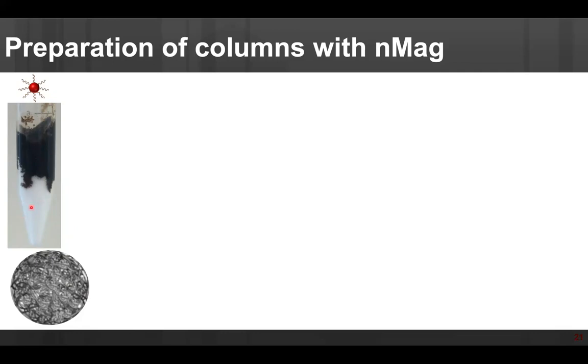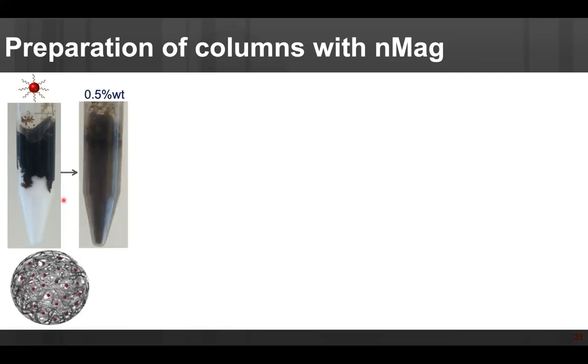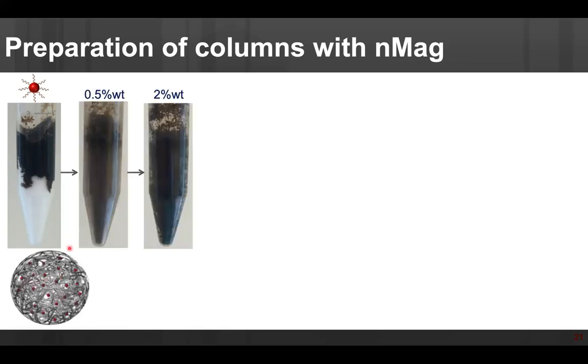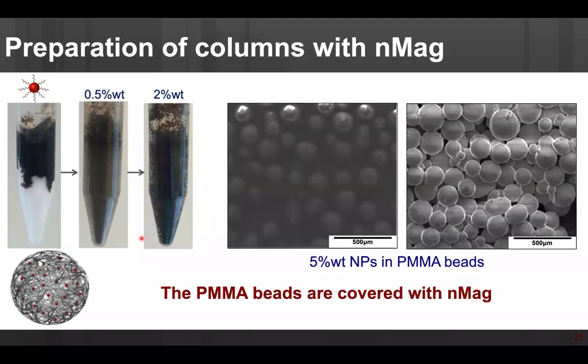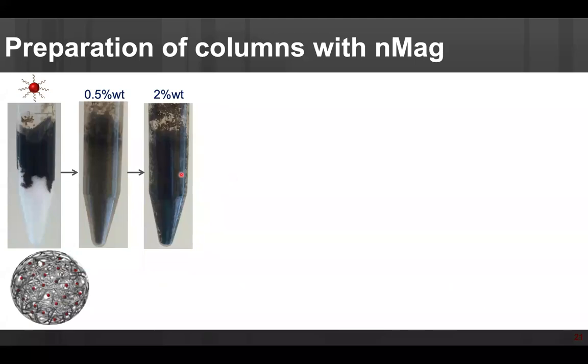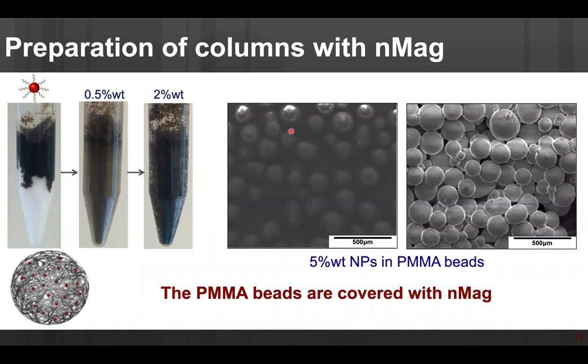So what I thought at that moment is, well, we have these nice polymer beads that we can use as a support. If we stick the nanoparticles on the surface, I start to saturate this one. And as much as I add, I think the highest that I added in here was 2%. And we can see how the bead changes before adding the nanoparticles to after adding them. Now we have a lot of contrast coming from the nanoparticles.